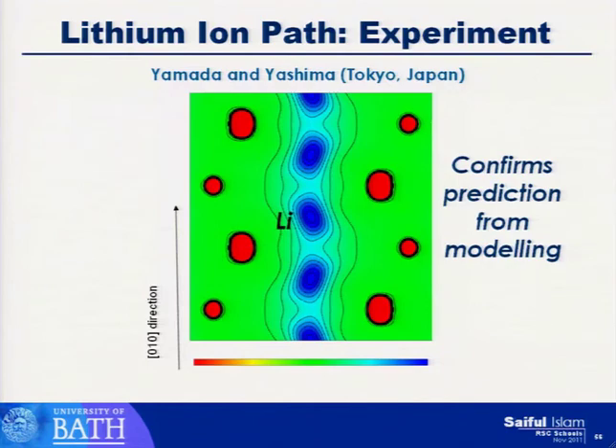And is there some experimental evidence for that? And there is. These are experiments carried out in Tokyo by Yamada and Yashima. And these experiments are based on very sophisticated neutron diffraction again. And they found, indeed, that the lithium ions are going in that 1D channel, but not in a linear path. It's actually going along this curved path. So it confirms our prediction from modeling this curved path. So that was one of the aims of modeling: can we be predictive? So that was quite nice. And we've extended this work to a whole range of other materials as well.